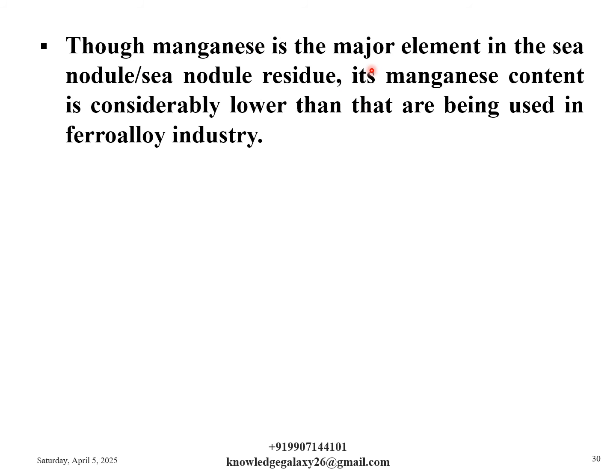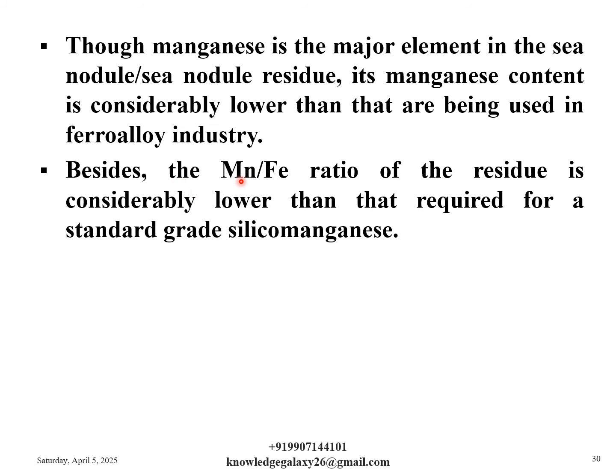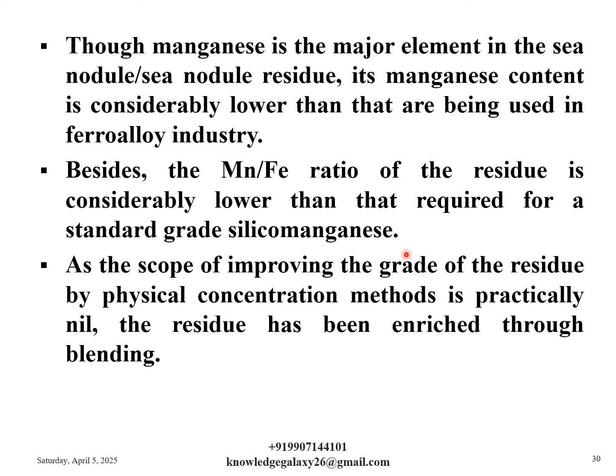Though manganese is the major element in the sea nodule or sea nodule residue, its manganese content is considerably lower than that being used in the ferroalloy industry. Besides, the Mn by Fe ratio of the residue is considerably lower than that required for a standard grade silicomanganese. As the scope of improving the grade of the residue by physical concentration methods is practically nil, the residue has been enriched through proper blending. A high-grade manganese ore or a ferromanganese slag has been employed for this purpose, that is, for the blending of low-grade manganese sea nodule residue.